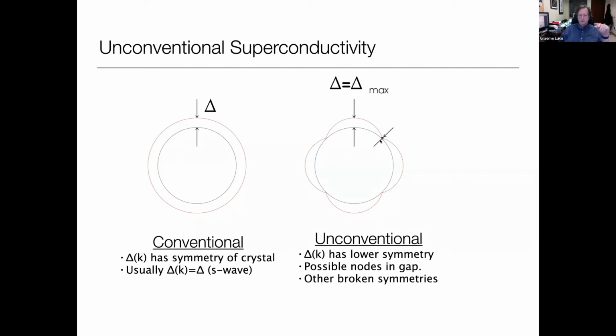An unconventional superconductor might be something like the cuprates, where this gap function has a lower symmetry. In fact, in the cuprates we have a so-called D-wave pairing state, where the gap actually changes sign at different places as you go around the Fermi surface, and actually has places where it identically goes to 0 because the gap crosses there. So an unconventional superconductor is one where the gap has a lower symmetry than the crystal structure that it's living in. In addition to this lack of rotational symmetry, there are other broken symmetries as well, and one of the most common ones that we spend a lot of time looking at is broken time reversal symmetry, which is in some sense fancy talk for an internal magnetic field being generated.